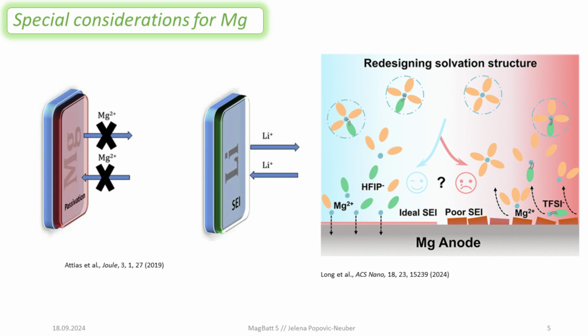But special considerations for magnesium, I guess you have seen this kind of sketch many, many times. In the case of lithium, generally on electrodes, we have an SEI that is an ionic conductor. So we can transport lithium through it, and we hope that it's not too resistive, so we do not have too resistive interfaces that are making problems in our cells, but in principle, we can transport lithium. In many cases, if we have a magnesium metal, we simply cannot get magnesium through it. So people call it a passivation. I would call it simply a very, very ionically blocking interface. So somehow we have to figure out how do we solve this.